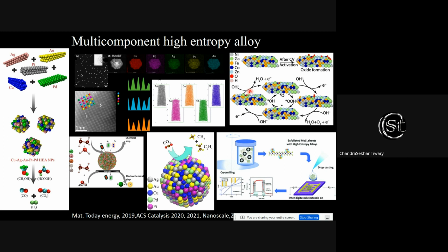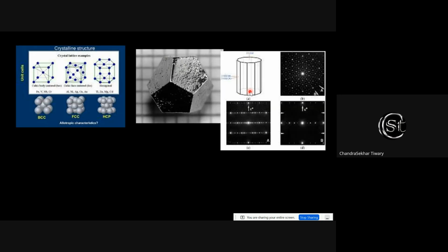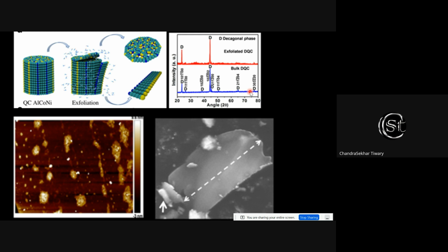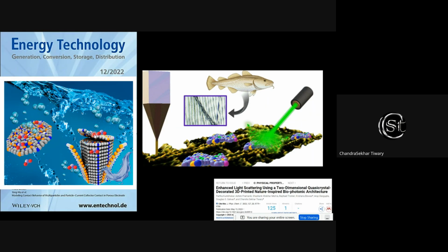Now, this is more related to the environment, generally, but another aspect of making 2D metals is that we can utilize quasicrystals, which can be a source to exfoliate and make 2D metals. For example, 2D aluminum can be made through quasicrystals. If you take aluminum, cobalt, and nickel, with cobalt and nickel in a very small quantity, you put them together and do the right surface chemistry, we can exfoliate them in 2D form. And it can be utilized for hydrogen generation, oxygen evolution, and also a lot of plasmonic work can be done using this kind of 2D material.